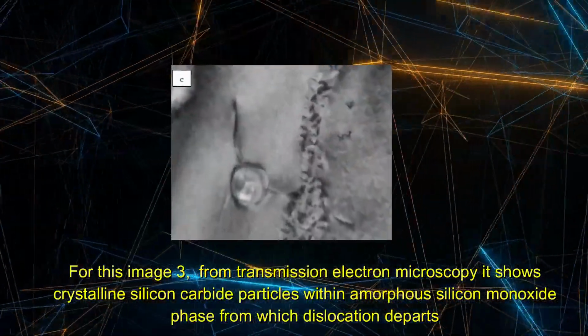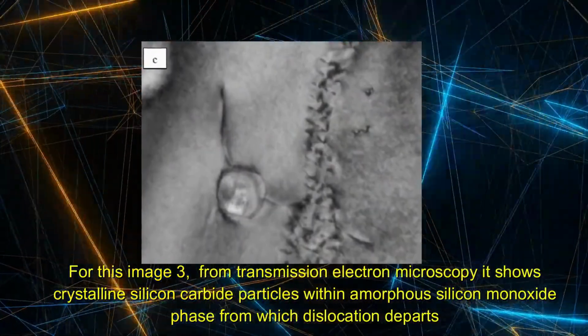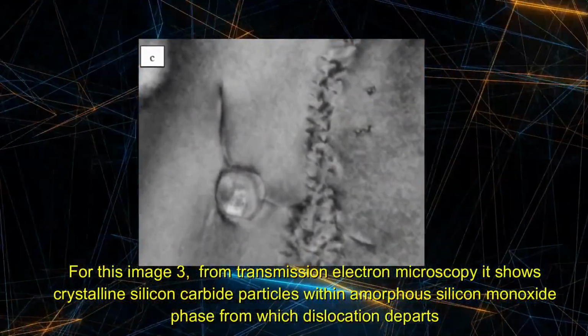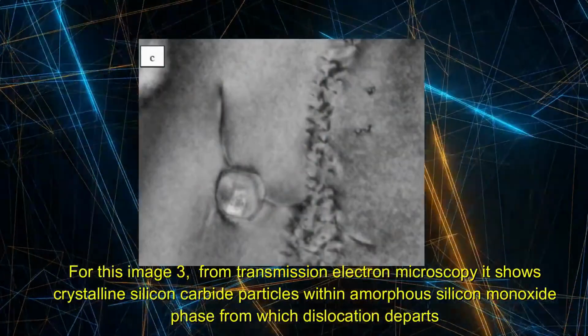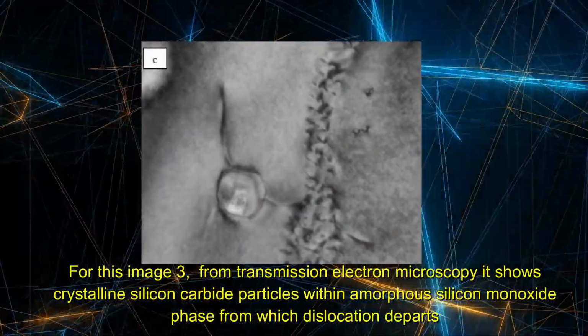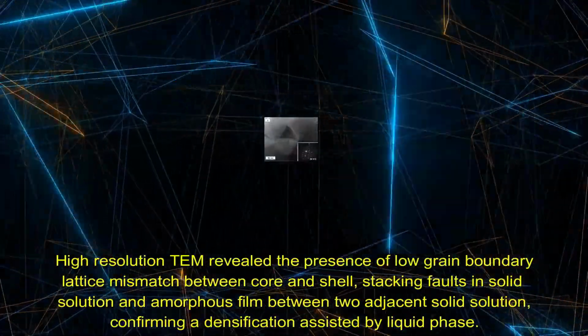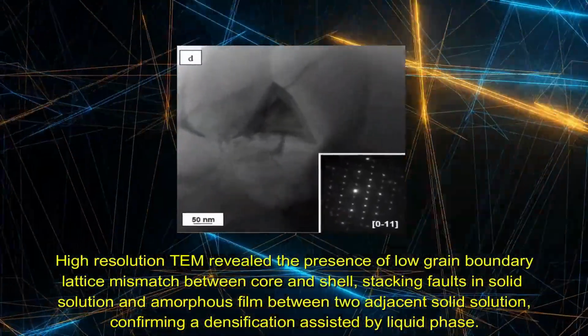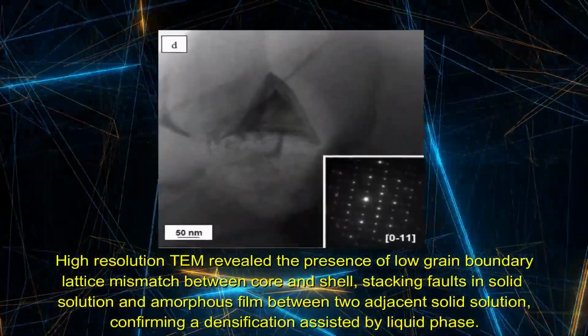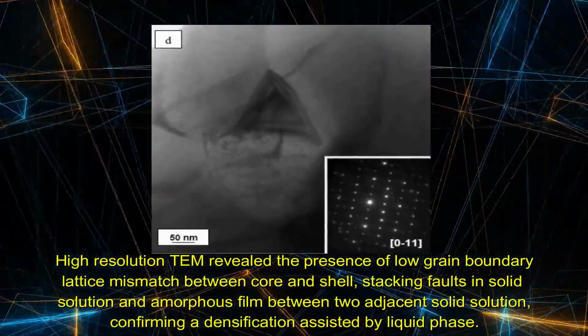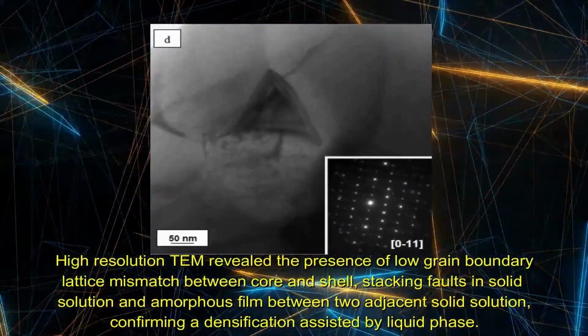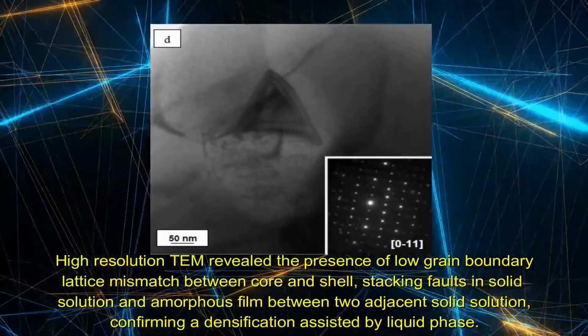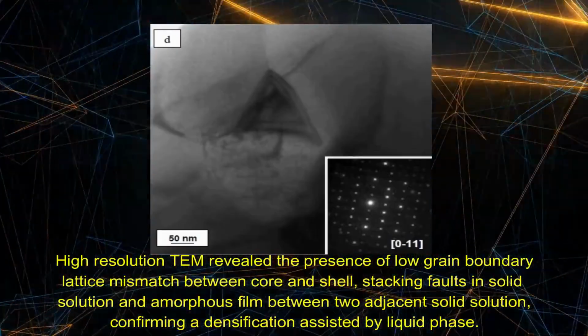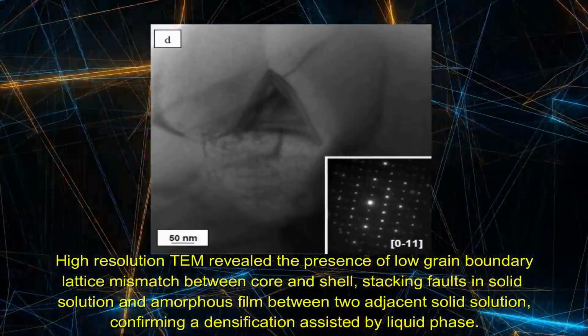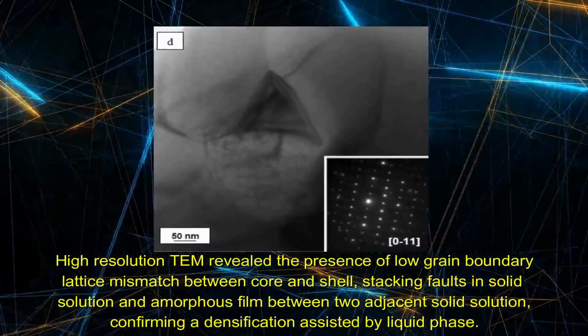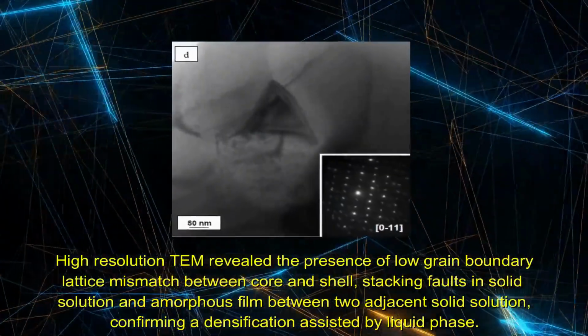This image seen from transmission electron microscopy shows crystalline silicon carbide particles within an amorphous silicon monoxide phase from which dislocation departs. High-resolution transmission electron microscopy revealed the presence of low-grain boundary lattice mismatch between core and shell, stacking faults in solid solution, and an amorphous film between two adjacent solid solutions, confirming a densification assisted by liquid phase.